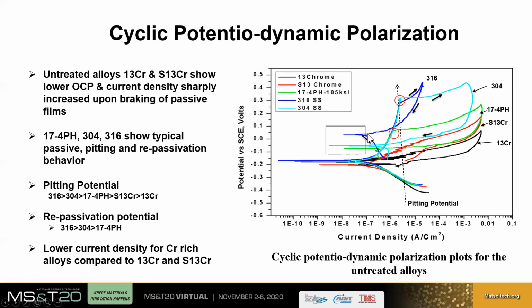From the plot, we can rank the materials based on pitting potential: 316 has a higher pitting potential than 304 and 17-4 PH. Repassivation potential is also higher for 316 and 304, and a lower current density was seen for the chromium-rich alloys compared to 13 chrome and super 13 chrome material.